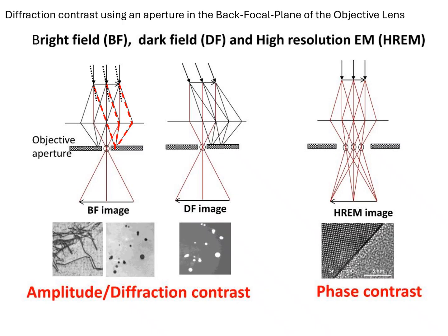For typical electron voltages between 100 and 300 kilo electron volts, the diffraction angles are often a fraction less than 1 degree. So they're a fraction of a degree. And these diffracted planes come out at different angles, and we can collect the intensity from diffraction at certain angles and focus that to what would be the points here.